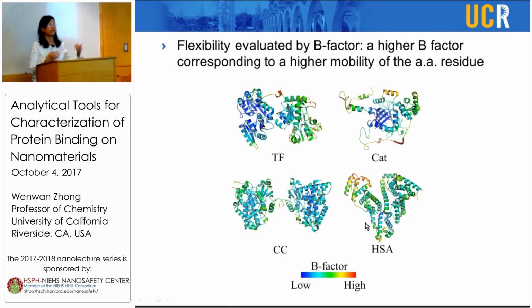Because if they already have structural flexibility, then once bound to the particle, the change could be more significant compared to, for example, a protein like HSA, which is already flexible. So the differences between binding or no binding to the particle would not be that large compared to the protein that has a lot of rigid areas, but some loop structures, highlighted in orange, are the highly flexible portions.